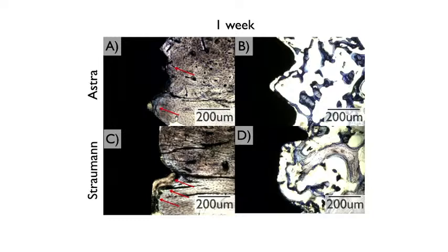So basically, you have a feeling of good stability, but this is fake, because what will happen is you have a lot of micro cracks. Those are those black lines. Because you put a lot of torque into the bone, you are going to crack the bone everywhere, and you're going to pay the bill because the bone is going to resorb, remodel, and reform.